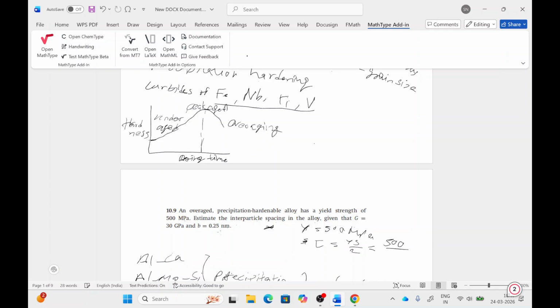So 500 by 2 will be 250, and we know the formula tau equals GB by lambda. We have to find the interparticle spacing, so lambda will be GB by tau. G is 30 GPa, B is 0.25 nanometer, so 10 raised to power 9 and 10 raised to power minus 9 will cancel out. We have given a strength of 250 megapascals, which is 10 raised to power 6.